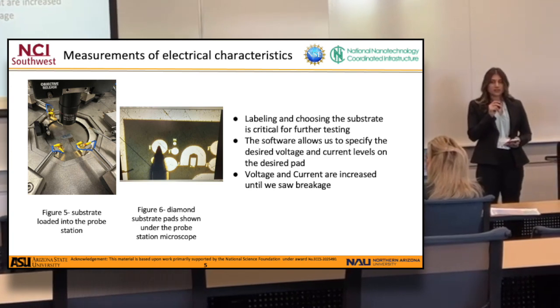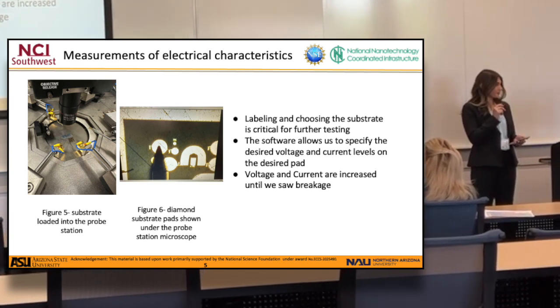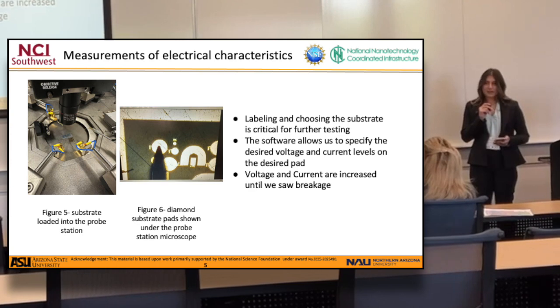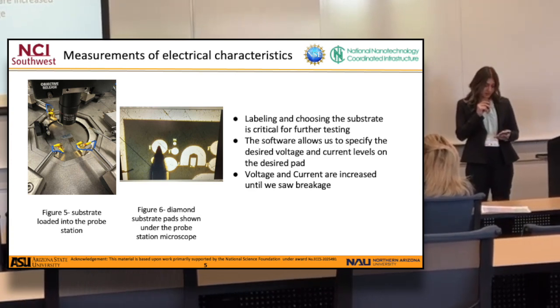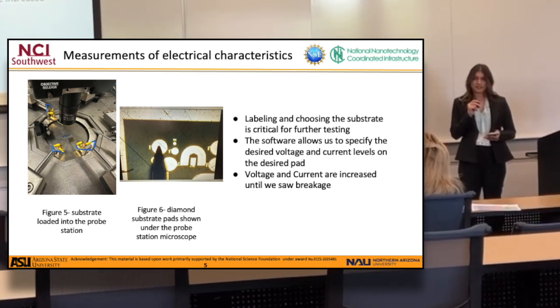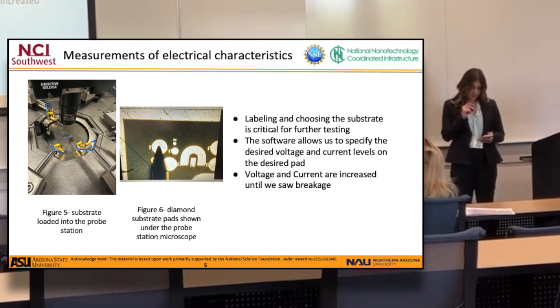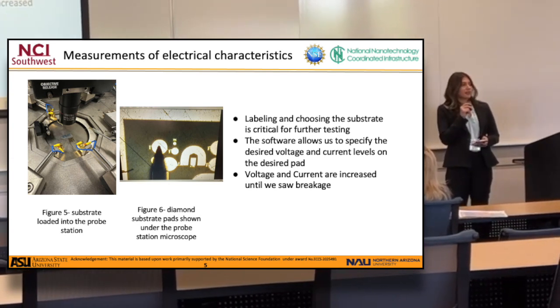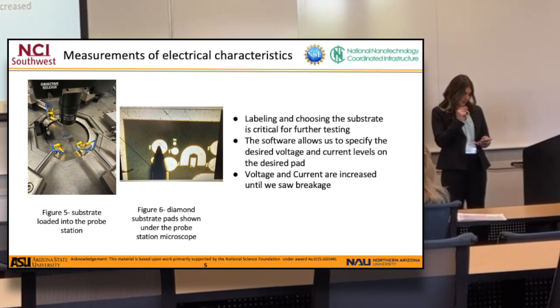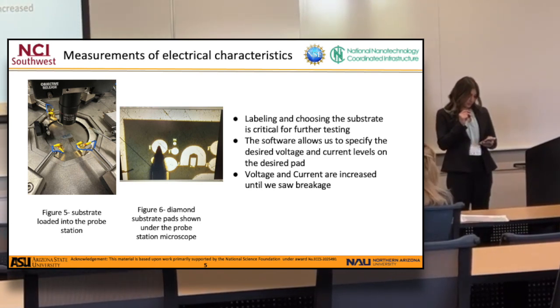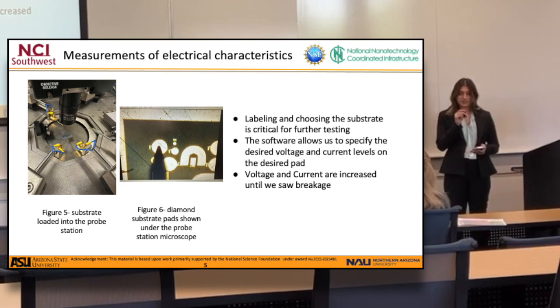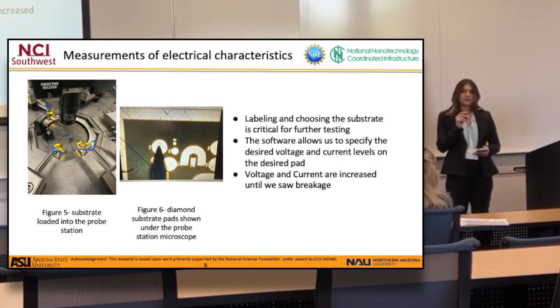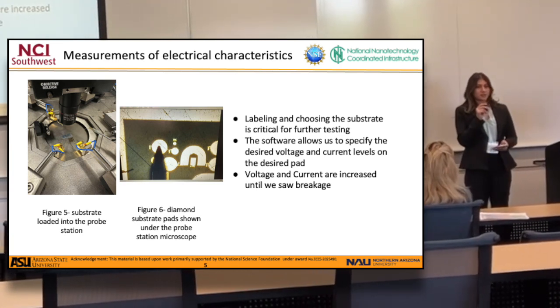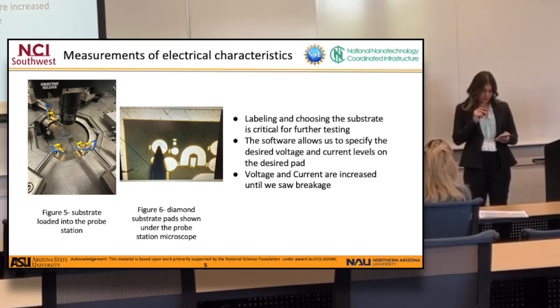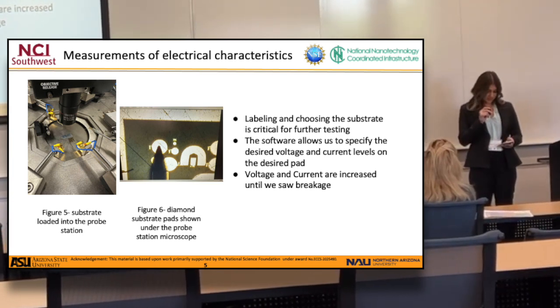Then we loaded our substrate into the probe station, and the live microscope feed was displayed on a media player, which allowed us to select each pad that we wanted to test. And the software that we used on the computer allowed us to apply the desired voltage and current to the pads. We increased the voltage by small increments until we observed its breaking point, and we repeated this process a few times on various sized circle pads.